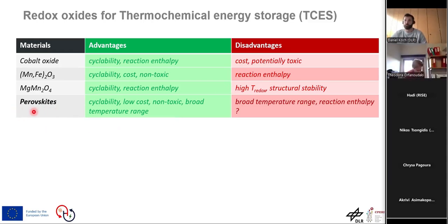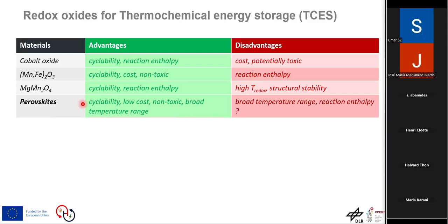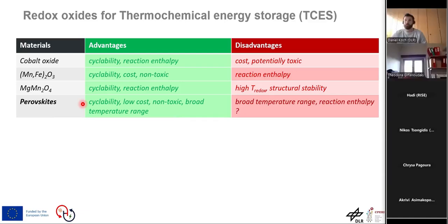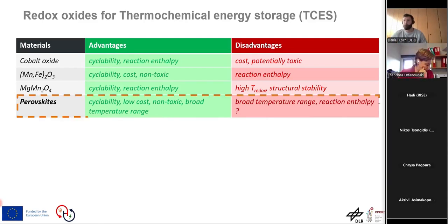Perovskites, on the other hand, are cheap if based on abundant materials, non-toxic, they operate at a lower temperature range, and they exhibit good cyclability. However, this temperature range may cause issues as well, and of course the reaction enthalpy is not as high as cobalt oxide, for instance. However, based on these advantages, if we click, we will see that in our project here, we will focus on perovskites.